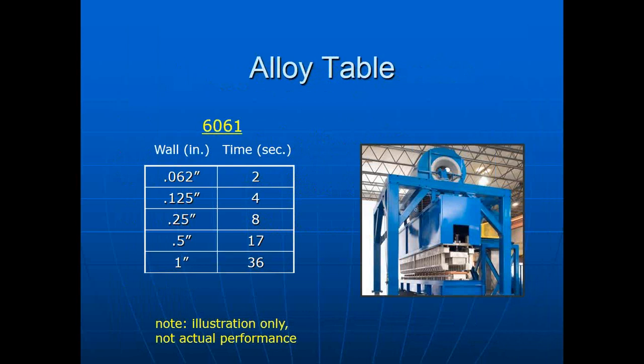The chart doesn't go any further, because if this is a 1.5 inch or a 2 inch wall, it's more than the time required to make rate. It's probably going to be about a 3/4 inch wall. It's probably going to be about a minute, and that's too slow a rate at 1200 degrees per second. Obviously, we only have about 45 or 50 seconds to get the job done.